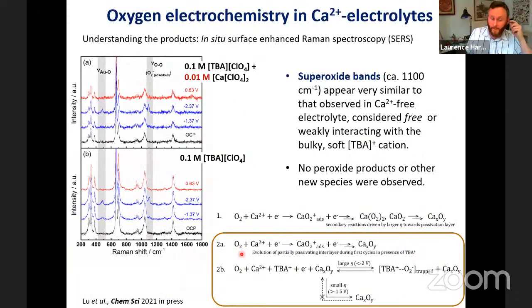And so we used surface enhanced Raman spectroscopy to again understand what the electrochemically active species is. And what we've seen is that we again see this oxygen stretch of the superoxide and the gold-oxygen stretch. So we can use Raman very nicely to identify some of the key species that are present on the interface.